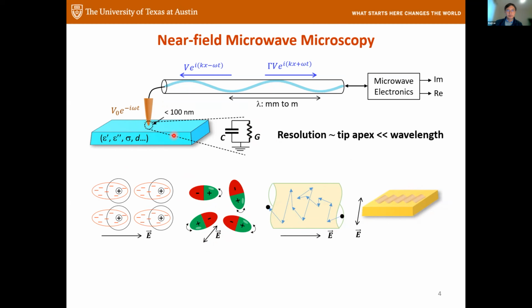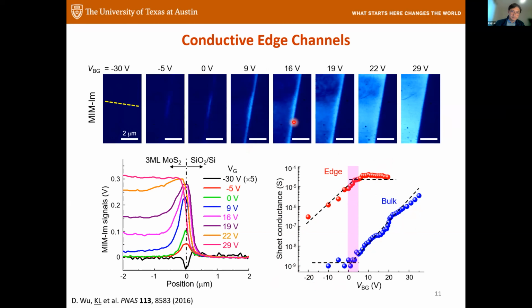and eventually the edge channel merges with the bulk. We can actually do simulation of the signal and calculate the effective conductance at the bulk and the effective conductance at the edge. And note that this is not infinitely high. So this means this is the edge. The edge is still lossy.